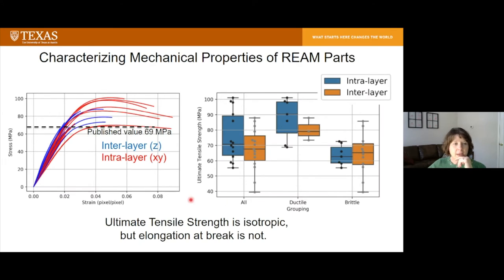So here we can see some of the mechanical properties from these parts. We were very pleased with what we saw. On the left-hand slide, you see a stress-strain plot. The black dotted line is the published value of strength for this particular epoxy resin, which is 69 megapascal. The red and blue lines are results from strength testing of some of the tensile bars that you saw on the previous slide. The blue lines are interlayer, so that is across layers, where we expect parts to be weaker. The red lines are within the layers.